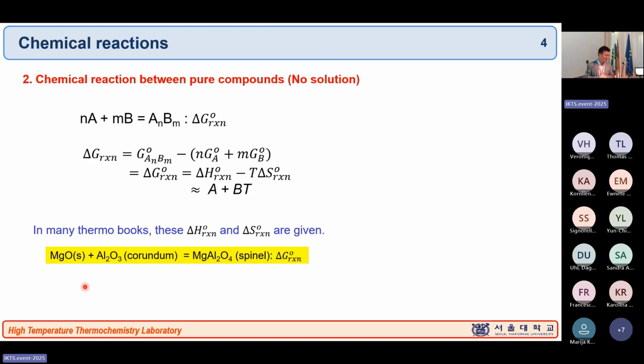And so Gibbs energy of reaction, okay, here you have two terminologies, delta G naught of reaction. This means the Gibbs energy change of the pure AB minus pure A minus pure B. That's what this means. But when we say globally, whether this chemical reaction goes forward or backward, you have to always look at delta G of reaction, okay? Because later I'll show you that your reactant or product may not be in the pure state. Then we have to have a general kind of formula. So that's why I want to introduce delta G of reaction.